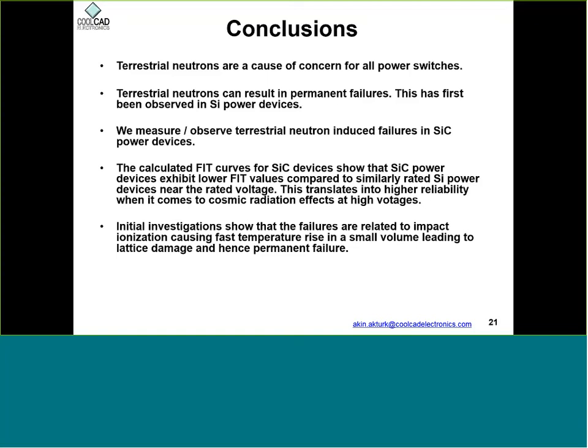And at high voltages, close to the rated voltage, if you compare a similar silicon and silicon carbide device, the silicon device tends to have a higher failure rate. But as you go down in bias, there's a crossover below which silicon carbide can have a higher rate. But at those levels, the failure rates are generally low, so for many applications, you may not need to worry about it. To mitigate these effects, circuit designers generally derate the parts. They use them at a lower voltage so that the failure rates are suppressed.